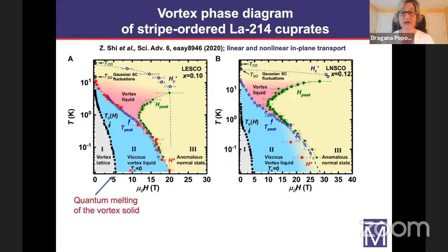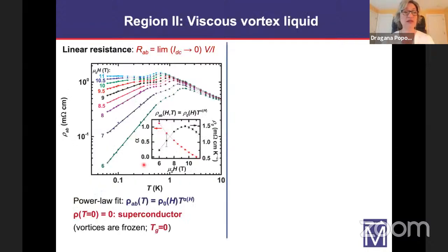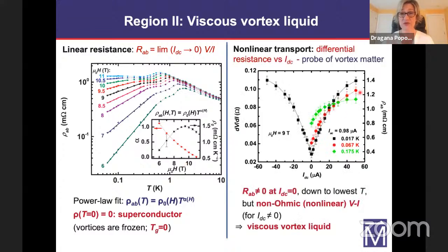So what does the behavior of the system look like in this intermediate regime that we are calling viscous vortex liquid? Well, the linear resistance, it turns out, is described best phenomenologically with a simple power law, as you can see here on this log-log plot. And this means that as temperature goes to zero, resistance goes to zero. In other words, the material becomes a superconductor at zero temperature. And as I already showed you, the transport is also non-ohmic. This is just one example.